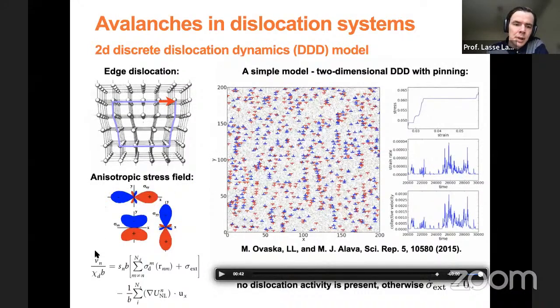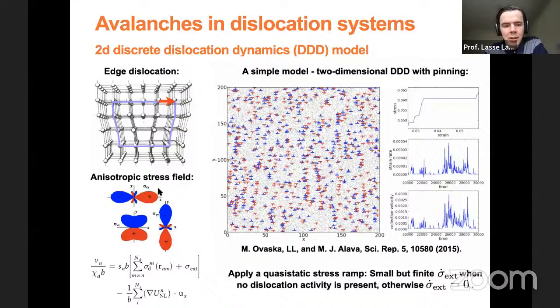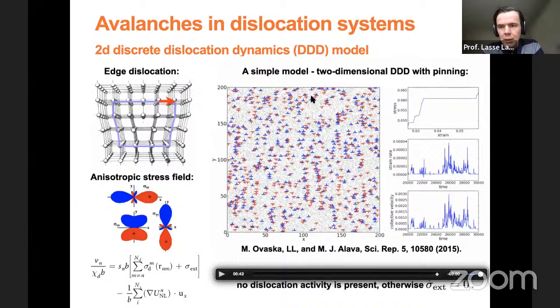So from elasticity theory, you can work out what kind of strain fields these objects are surrounded with. So they look like this, so they are complicated, long range, anisotropic. So that gives rise to some interesting phenomena, like some patterning that you end up having here. So these are not just some gas particles that are randomly dispersed in this medium, but they form some structures there. And so here are the equations of motion.